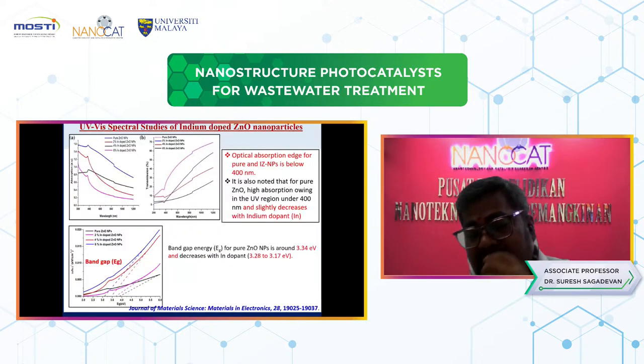And then there are the optical absorption studies. Look here, the maximum absorption for pure and indium doped nanoparticles is below 400 nanometers. It is also noted that zinc oxide has high absorption in the UV region, and the band gap values are calculated by using the Tauc plot.